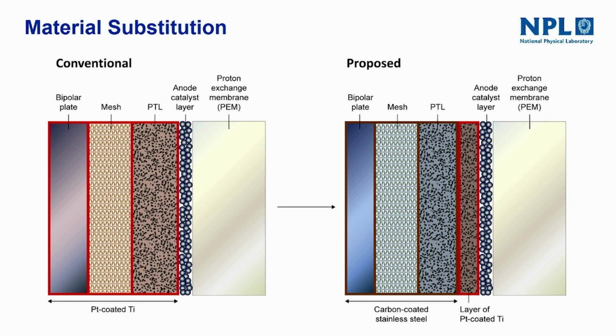You have the catalyst layer, and everything to the left of it is platinum-coated titanium: the porous transport layer, the mesh, and the bipolar plate. Our idea is we can replace all of these materials with carbon-coated stainless steel as long as we have a thin, couple of hundred, maybe 300 micron thick microporous layer that could be platinum-coated titanium or other corrosion-resistant material, just to provide a buffer through which the potential drops in this corrosive zone. And this could really drop the cost of these stacks if this idea could be rolled out.